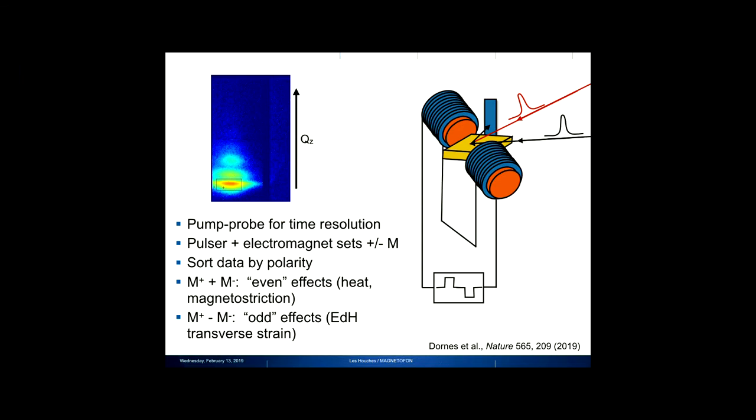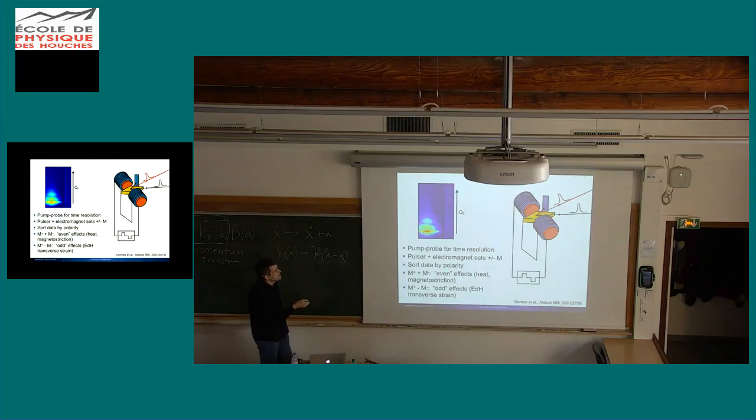And the way we do it is we do a clever trick where we're doing the experiment over and over again with a random initial polarity of the magnetic field, because one of the characteristics of the transverse acoustic wave is that its direction of displacement will depend on the direction of the initial magnetization, because the angular momentum will depend on the direction of the initial magnetization. So that means that the actual lattice motion and the phase of the response that we see will flip by 180 degrees if we reverse the initial magnetization.